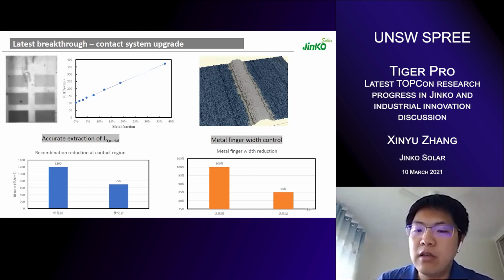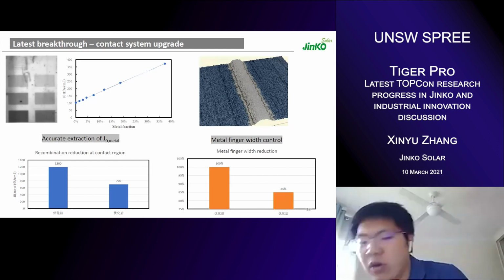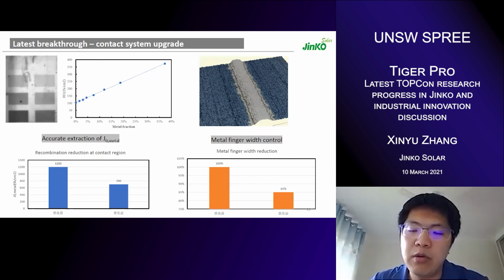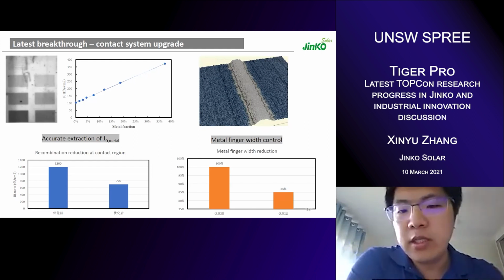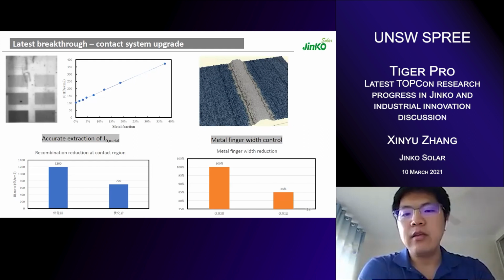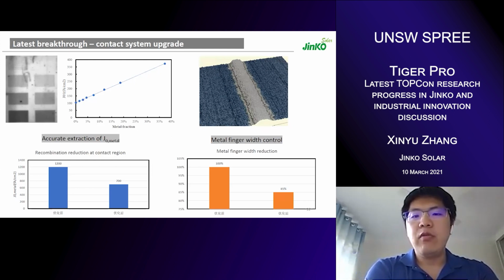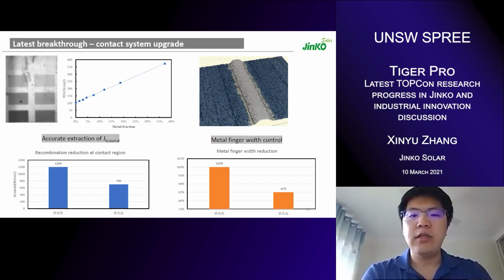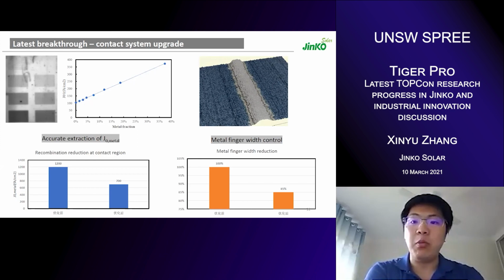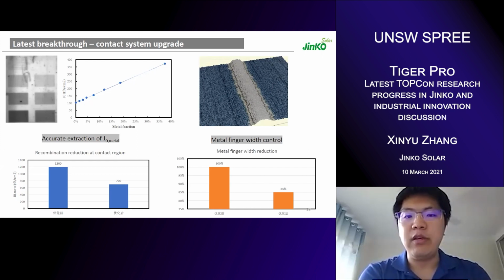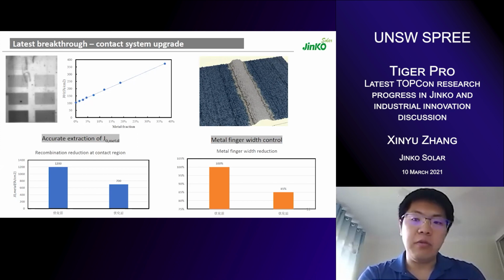And finger width control is another important research topic for us. We are now able to make a wafer with the finger width close to 25, which is very thin. For mass production it is also possible, but normally at the mass production level it is still sitting at more than 30. So there's still a very nice gap that we can fit, which will definitely improve the efficiency, as well as reduce the expensive metal consumption.